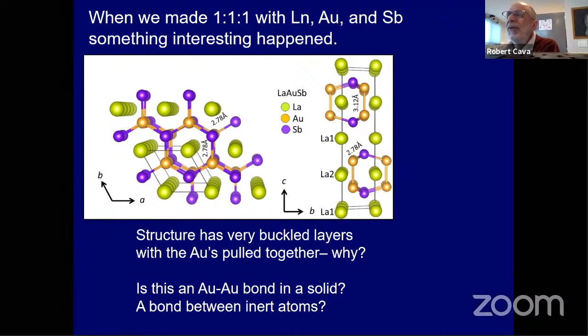And so now we made this compound, which is lanthanum, gold, antimony, and this stupid thing, we have this kind of bond between the golds. So the golds are on top of each other, and they are staggered. So there's not a continuous chain of gold here. There is a discrete gold-gold dimer. Why is that? Where'd that come from? Well,